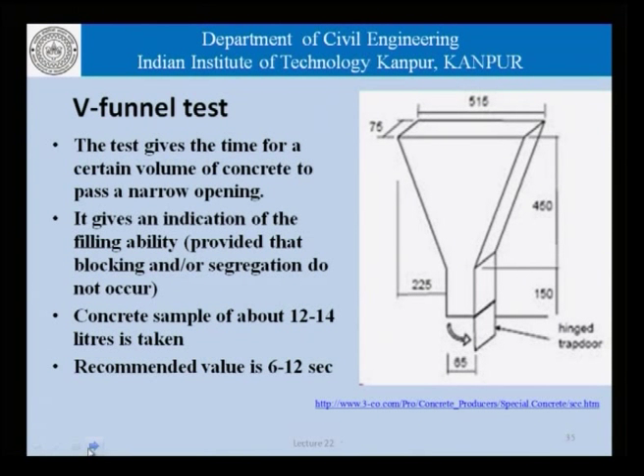Concrete samples would depend upon the size of the V funnel. It could be about 12 to 14 liters, and the time would vary between 6 and 12 seconds. So, if we have concrete filled in this funnel, which measures about, say, 500 millimeters on the top, has a width of about 75 millimeters here and a height of 450 millimeters with a constricted region here of about 150 millimeters, what we expect is that the concrete filled in this portion here, there is a lid which, when opened, allows the concrete to flow through this. And the time that it takes for the concrete to flow through is the V funnel time.